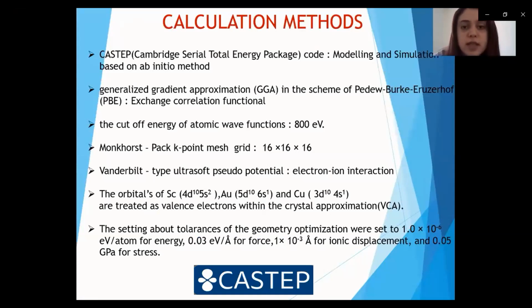Calculation methods. The CASTEP code is modeling and simulation based on the ab initio method. We choose the generalized gradient approximation in the scheme of PBE, exchange correlation functional. We choose the cutoff energy of atomic wave functions at 800 eV. Monkhorst-Pack k-point mesh grid is set to 16. Vanderbilt type ultrasoft pseudopotential for electron-ion interaction. The orbitals of scandium, gold, and copper are treated as valence electrons within the virtual crystal approximation.